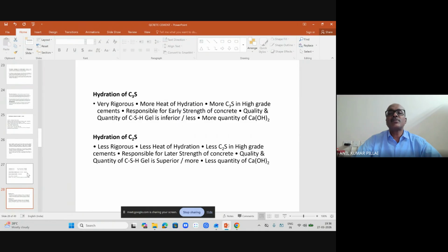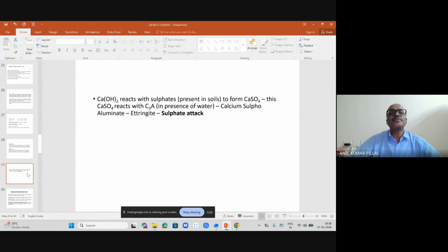It is responsible for the early strength of concrete, and more calcium hydroxide also comes out. Of course, C2S is less reactive as compared to C3S, and in comparison to that, you will find that calcium hydroxide would be lesser. So this is what happens in case of sulfate attack, and this reacts with C3A.